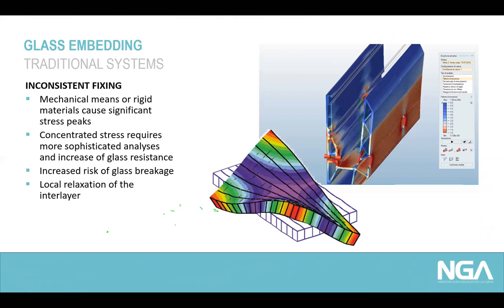Increase of glass resistance can be achieved by using stronger glass types or by increasing the glass thickness. Furthermore, local stress peaks or local concentrated stress can cause local relaxation of the glass interlayer, the laminated glass interlayer, and that can get the glass unit loose in the system and could require some further maintenance effort.